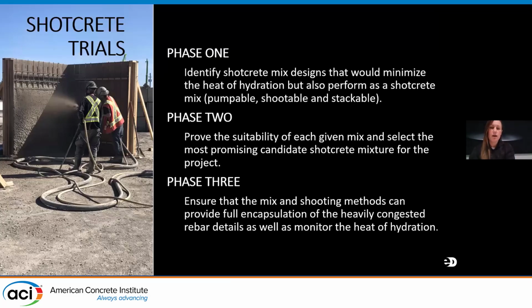Unlike the mixtures that we already accepted, additional considerations were needed when developing a shotcrete mix, mainly the stackability of the concrete. And then a fun wrench that was thrown in by the Shotcrete contractors was that they typically can't shoot a mix with more than 20% slag, as it's really hard to keep that stackability. So 20% is really far from our desired 70%. So we knew that we had some work ahead of us. So a 3-phase research program was carried out to select a shotcrete mix that would meet all of the specified durability parameters, maintain the low heat of hydration requirements for mass concrete, and be pumpable, shootable, and stackable.